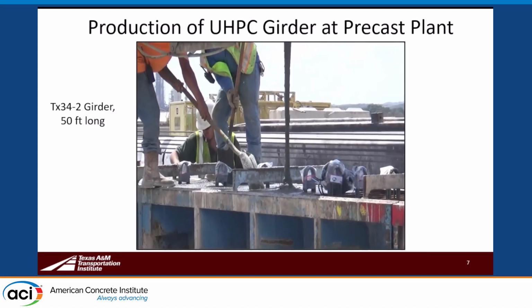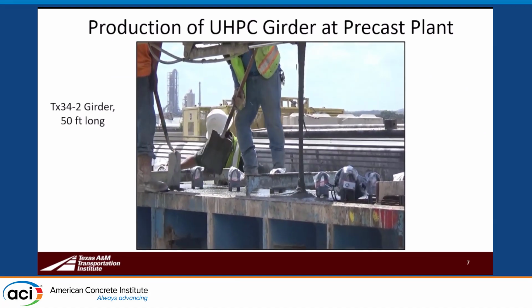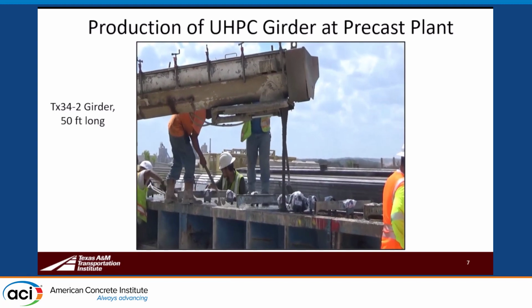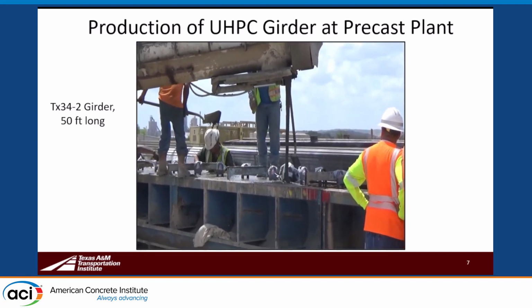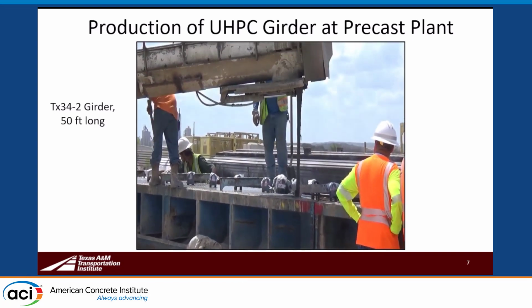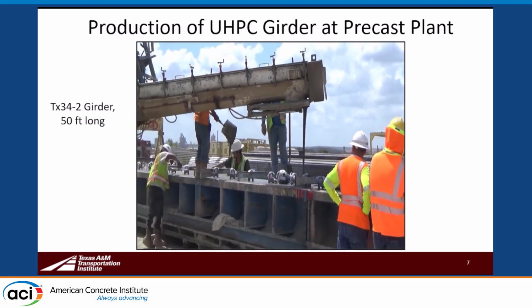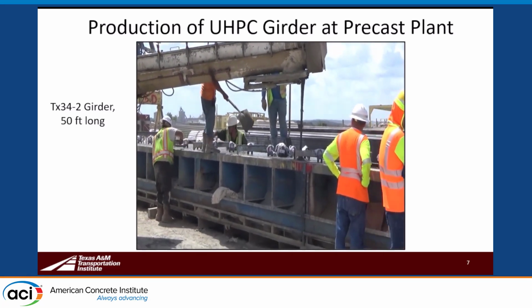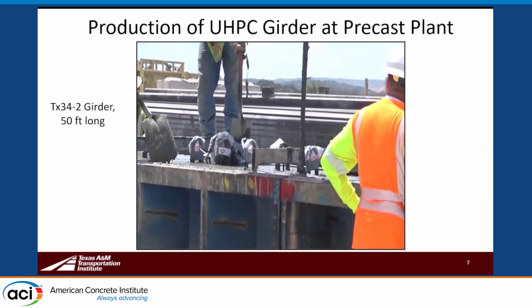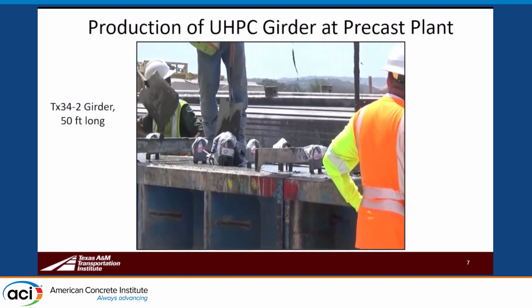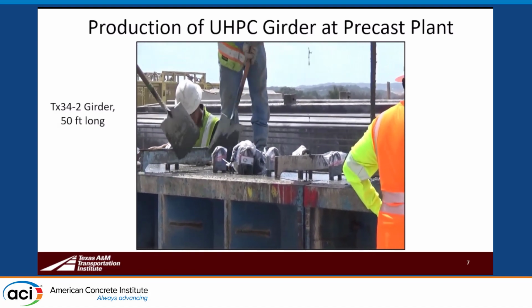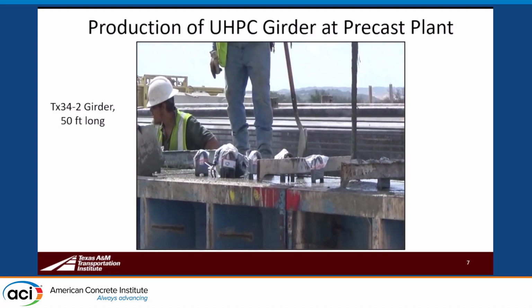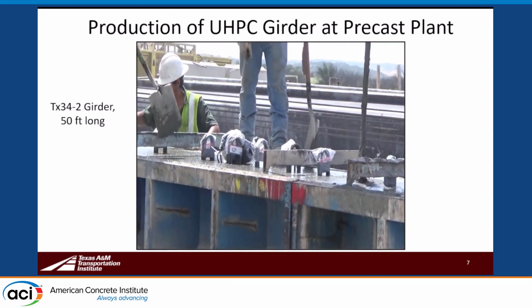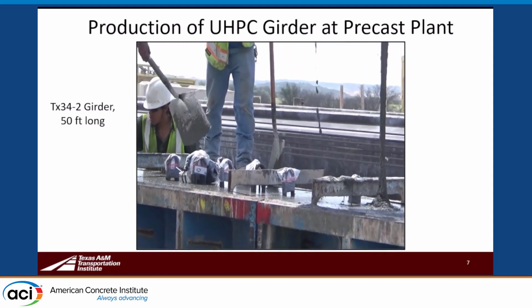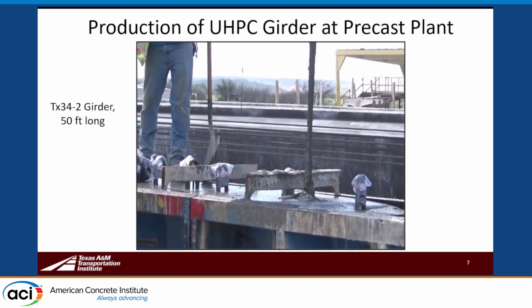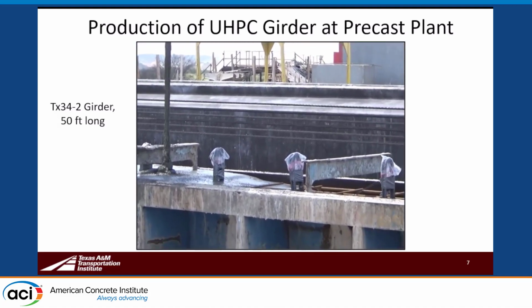So this is just a quick video showing the casting of our second girder specimen. You can see that it's a very flowable mix. There are no coarse aggregates in this mix, and so it's a very fine particle, dense, well-packed matrix that's designed such that it has very low porosity after it's hardened. As you can see, they're just topping off the girder at this point, and it's flowing down into some of the adjacent areas that were a little bit lower.